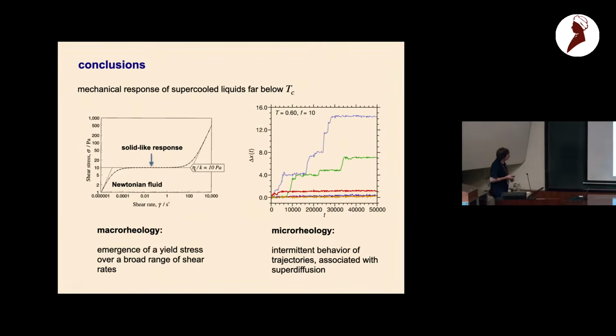So I come to the conclusions. I presented two themes: one, macrorheology - this was a proof of concept for the emergence of a yield stress, and we see that we can have access to Newtonian fluids at very low shear rates by applying a hybrid swap Monte Carlo MD technique. Then for the microrheology, the characteristic is this intermittent behavior of the trajectories, so that we have two populations, mobile and immobile particles. Thank you very much for your attention.